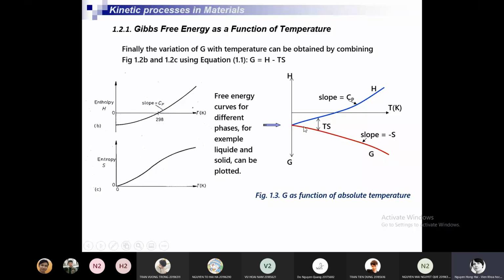And the slope of this free energy curve is minus S. Here, minus S. So you see, we can compute the free energy curve from the enthalpy and entropy curves and this equation. We combine these three elements, and we can find this. And you can see that the free energy of the system decreases with temperature. The higher the temperature, the lower the free energy of the system.